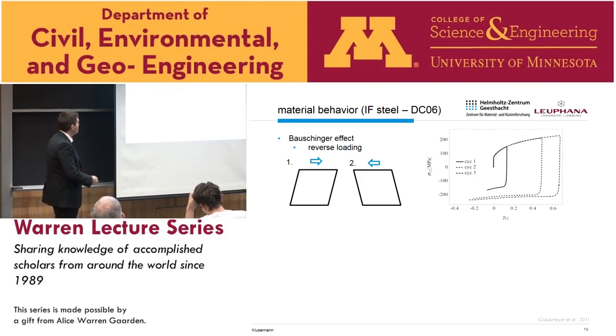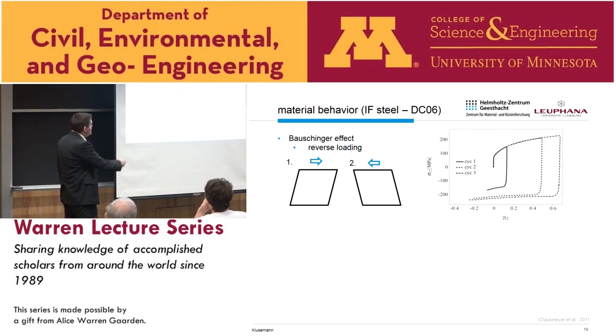In particular, they first show a kind of kinematic hardening behavior, also classified as the Bauschinger effect. You can imagine that you have a reverse loading: you first load it and then load it in the other direction, and you see a different yield point. You don't have the same yield position as in your loading; in the unloading it yields earlier, it can be deformed earlier.